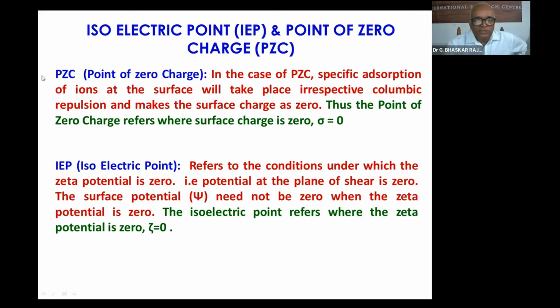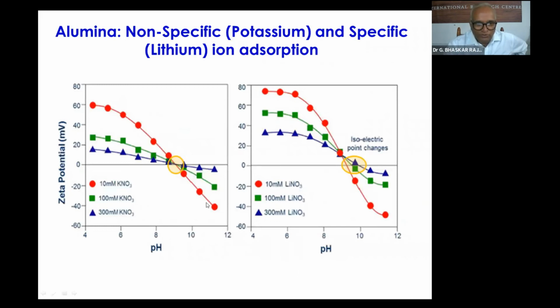Also there are two terms in this: point of zero charge and isoelectric point. Now let us go to this particular example. Here you have different concentrations of 10 millimolar, 100 millimolar, and 300 millimolar. You have performed the zeta potential measurements at different ionic strengths. So you have used potassium nitrate, KNO3, and in this case, lithium nitrate.